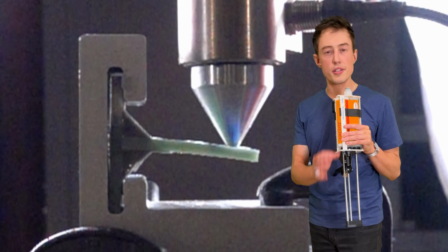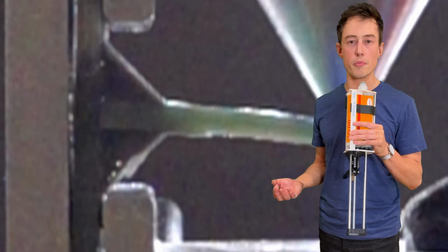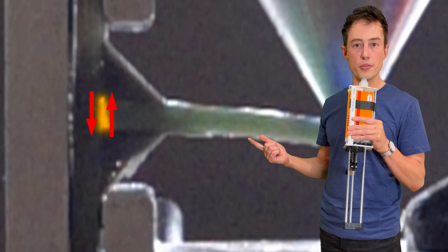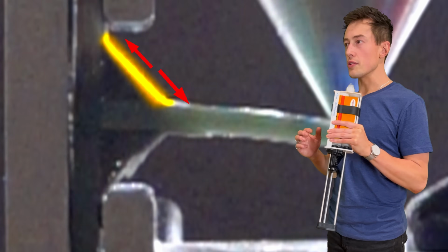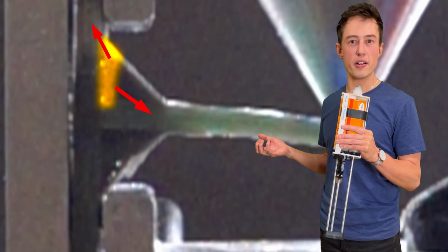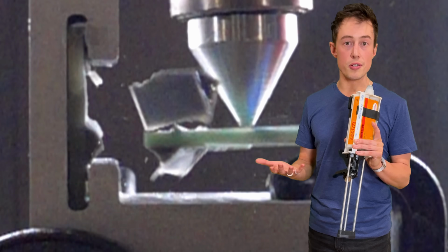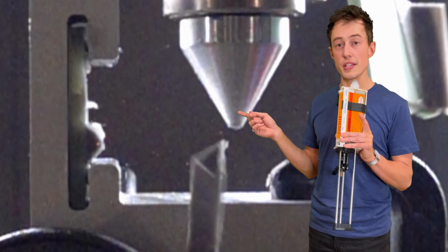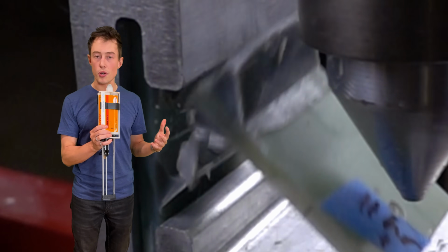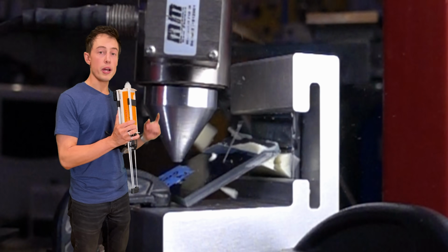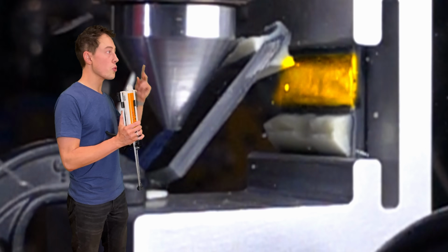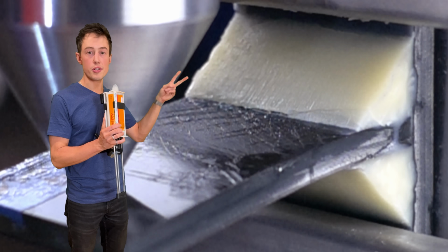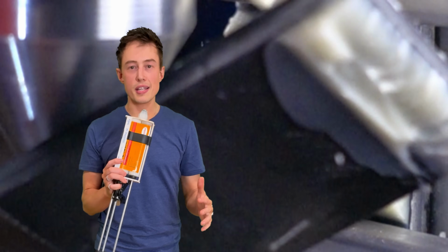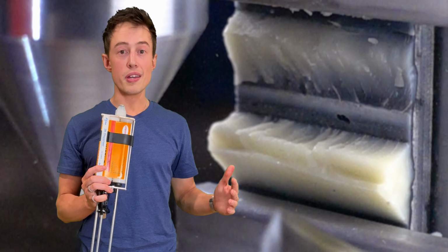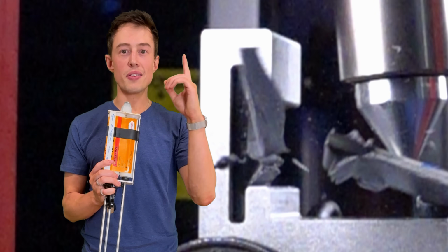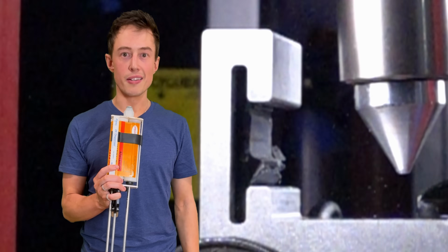Looking at a cross-section, there's a little bit of everything in this test setup. There's some compression here, some shear here, some tension here. There's a little bit of tension and shear in this area. In hindsight, I wish I had run lap shear tests, because the failure mode for most of these tests was about the same. Each test broke at a different strength, but they all failed by either shearing off at this surface or breaking in some combo of tension and shear around that area. But hindsight is 20/20, and say it with me, imperfect data can still have value. Let's begin.